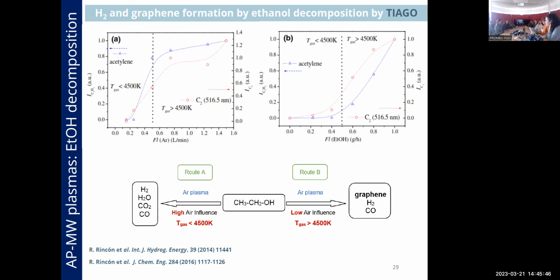It's important because it would be necessary to understand the formation of graphene, to understand that the fact that the discharges generated with the torch are open to air gives us a clue of how the process is taking place. Here we are observing two different routes for the decomposition of ethanol. The first one takes place when air has a stronger influence on the kinetics, and plasma gas temperature is always below 4,500 kelvins.